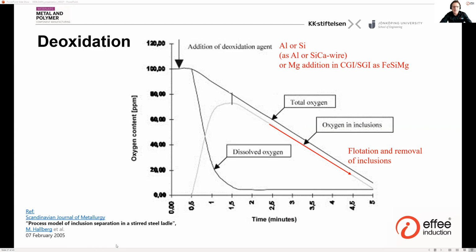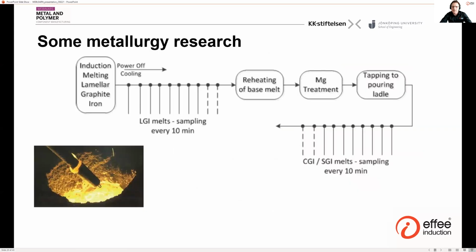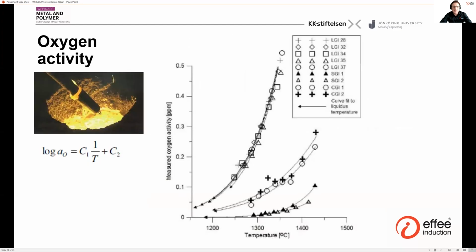So we can take the next. So I thought we could look at these equilibrium reactions a little more in detail from my own research. We performed a number of lamellar, compacted, and ductile iron melts, and then measured dissolved oxygen, chemical composition, temperature, and we also took slag samples for all these three main cast iron melt sorts. So we can take the next picture.